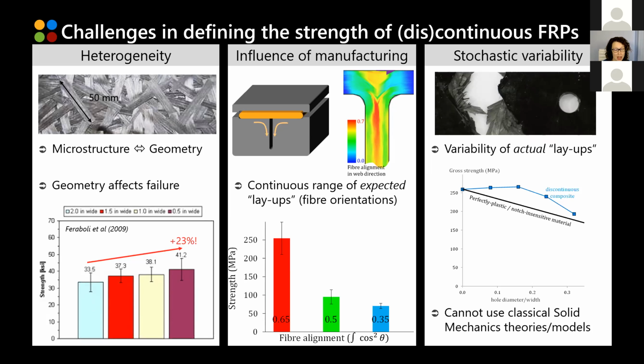discontinuous composites. And one of the main reasons why this happens is because at the scale of the reinforcement, we don't have a homogeneous and we don't have a uniform stress field. So each tow is going to see a completely different stress field in its own coordinate system. And we also have a stress field which is not uniaxial.